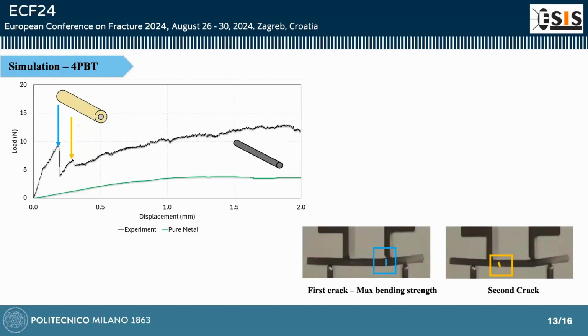In this slide, we are comparing the output of the 4-point bending test of the composite with the simulated pure metal core. And we see that while the cracks are happening, the resistance of the composite filament is still more than the pure metal. It means that although the shell is going to break, it is still working and adding strength to the composite filament.